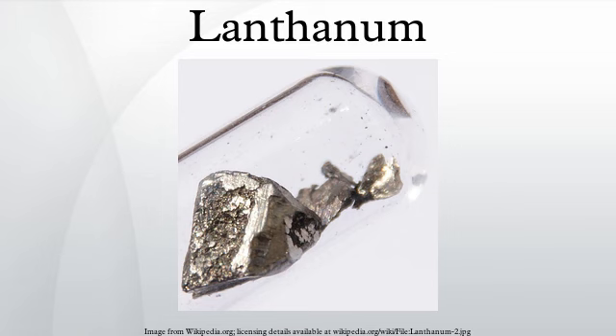Mish metal, a pyrophoric alloy used in lighter flints, contains 25% to 45% lanthanum. Lanthanum oxide and the boride are used in electronic vacuum tubes as hot cathode materials with strong emissivity of electrons. Crystals of LaB6 are used in high brightness, extended life, thermionic electron emission sources for electron microscopes, and Hall effect thrusters. Lanthanum fluoride is an essential component of a heavy fluoride glass named ZBLAN. This glass has superior transmittance in the infrared range and is therefore used for fiber optical communication systems.